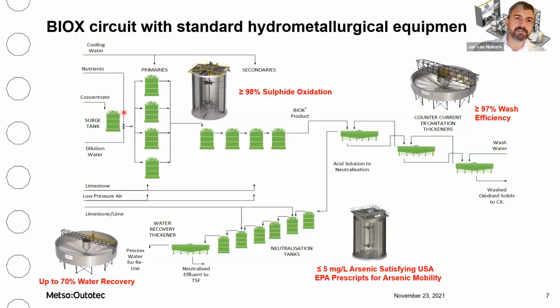Nutrients in the form of a fertilizer type, nitrogen, potassium, and phosphorus, are added to the feed to the BIOX process, as well as dilution water to feed the process at 20% solids. The important engineering requirements during the BIOX process are the cooling of the process, and we do this using internal cooling coils as well as evaporative cooling towers, and the supply of low pressure air to supply oxygen for the oxidation process. The process will normally operate at 40 degrees Celsius. The materials of construction for the BIOX reactors is typically stainless steel, although mild steel rubber-lined reactors can also be used.